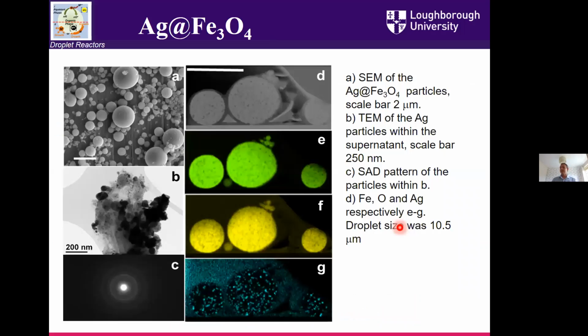We wanted to put the iron oxide in there. This was the first example of that with silver and iron oxide. And so you image these at the end of that process. We got these nice spherical particles. All of these have been extracted by a magnet, so we know they're magnetic. We know they've got iron oxide in there. But we noticed before we even started to do a lot of analysis on them that they're very polydisperse in their size. When you make the emulsion droplets, in theory, they're very regular in the size that you make them, and it usually results in a very uniform iron oxide spherical particle.